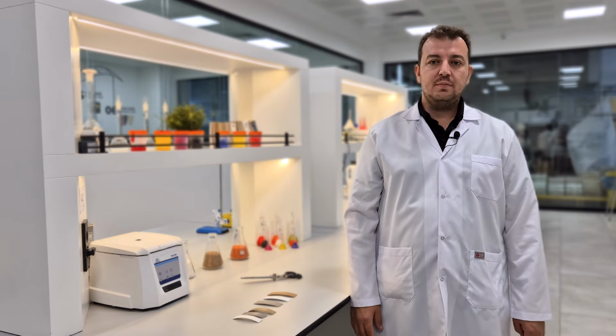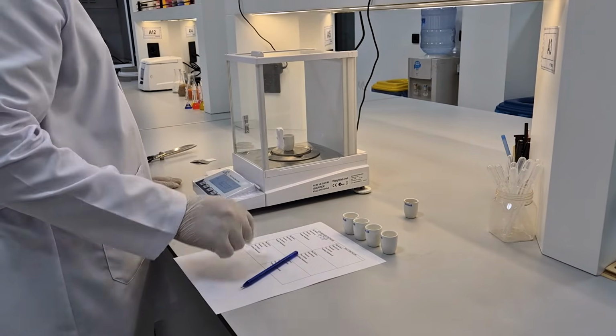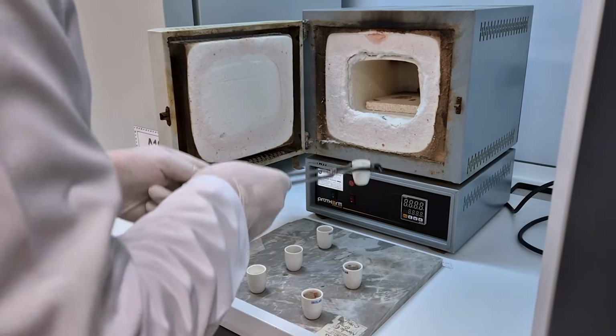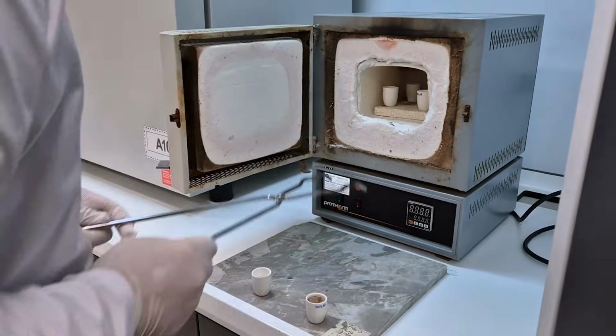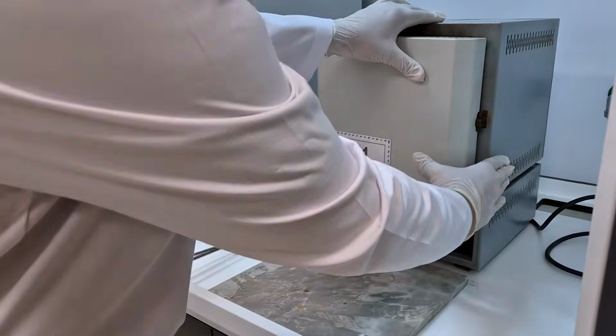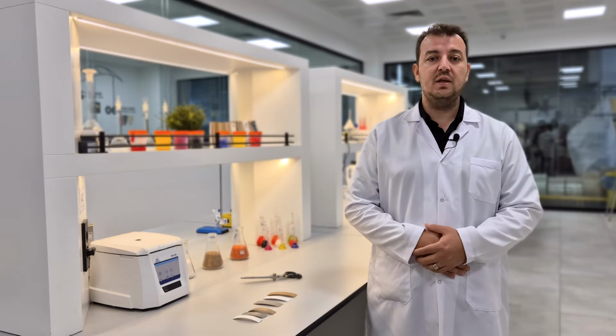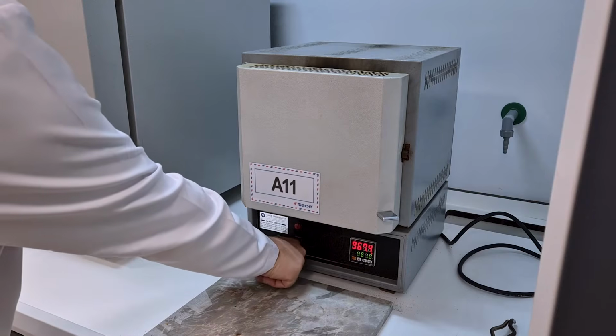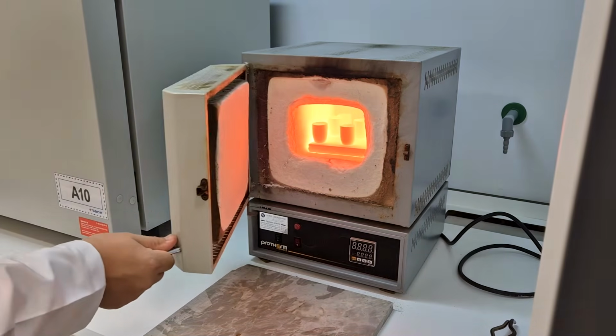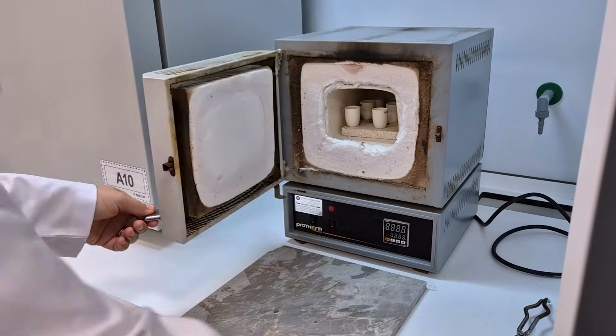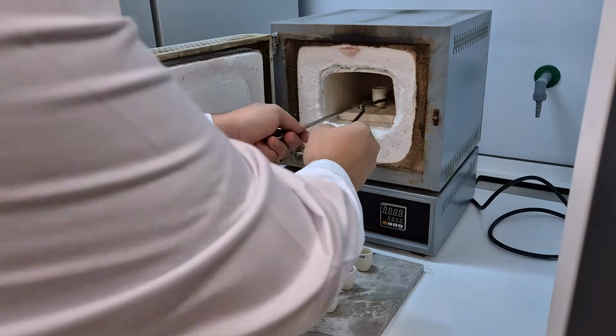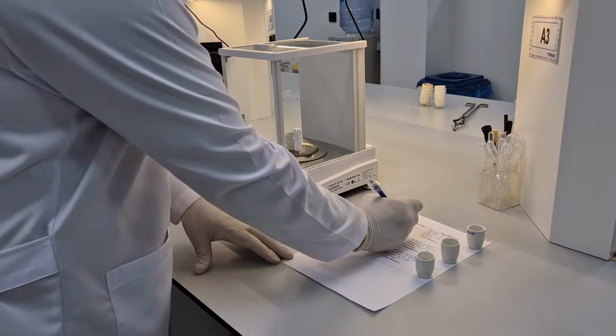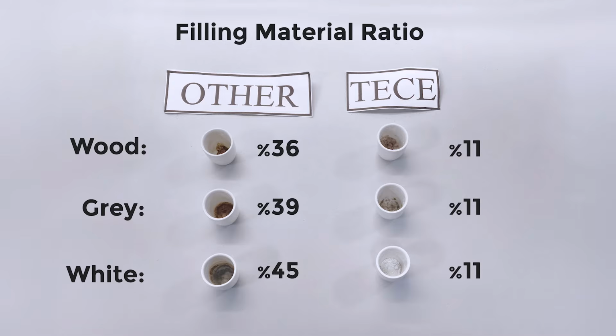In an inorganic material analysis conducted in a kiln at 960 degrees Celsius, it was found that the other cheap edge banding contains about 4 times more inorganic material than the amount of filler Tece uses. This reduces flexibility and makes the product brittle. Additionally, the excess inorganic material causes cutting machine blades to dull much faster than normal.